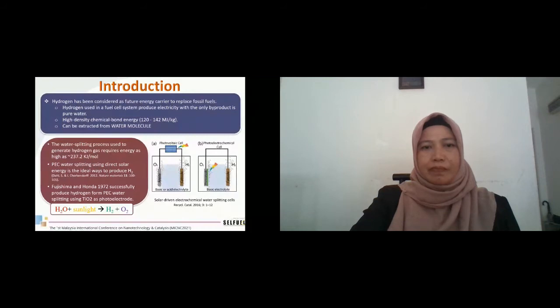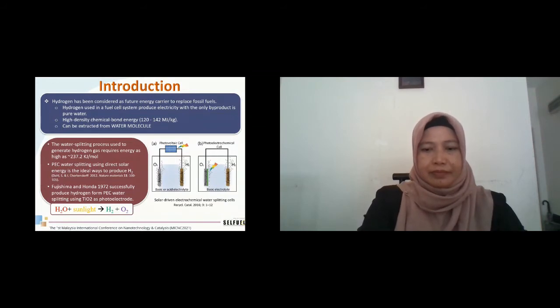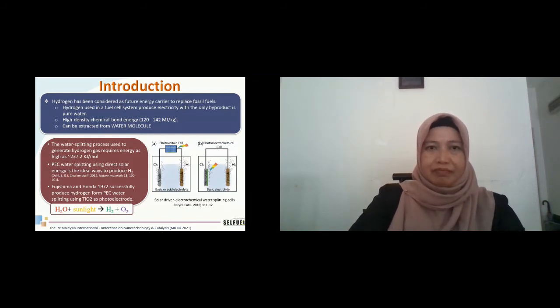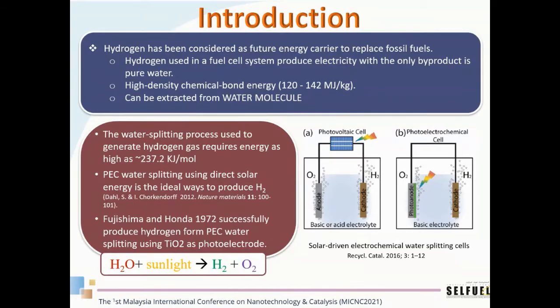One of them is using sunlight energy through the direct photoelectrochemical method. In the PEC method, water molecules split directly in situ with a simple and space-saving system compared to the conventional solar hydrogen system, which employs an electrolyzer and PV panel. This PEC method for water splitting was first reported by Fujishima and Honda in 1972. They used TiO2 as a photoelectrode material, and until now, this hydrogen production method is still under research because the efficiency and stability of the photoelectrode are still below the US DOE requirement for commercialization.